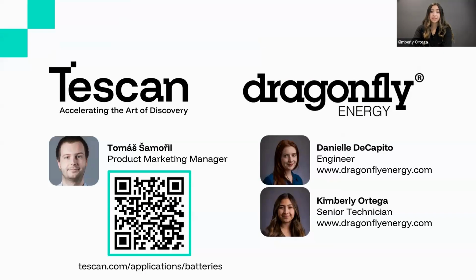So to summarize, we presented a multimodal approach for evaluating porosity in our dual-coated lithium-ion battery electrodes by using 2D cross-sectional SEM, which gave us fast initial insights, 3D FIB-SEM tomography, which eliminated preparation artifacts, and X-ray micro-CT, which was non-destructive and used for bulk analysis of total porosity. Each technique has its strengths and limitations, as we discussed, but together they offer a comprehensive picture of the electrode's microstructure. Thank you all for your time.